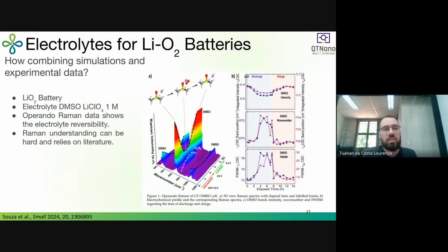So the second work that I want to show you is the investigation of the mechanism in the charge and discharge behavior of the electrolyte containing DMSO and lithium perchlorate, also in a lithium oxygen battery. This is also a collaboration with Professor Gustavo Doubek. And here, what we saw was, so they measured using operando Raman the behavior of the electrolyte when they charge and discharge the battery.